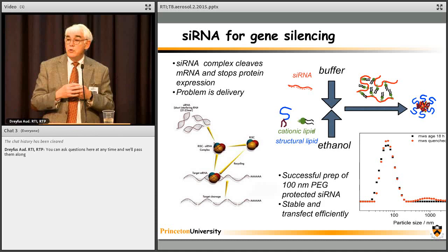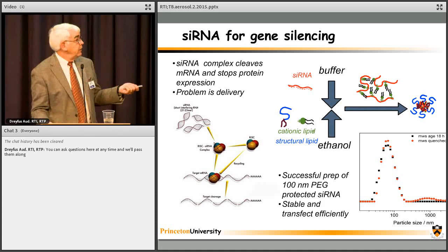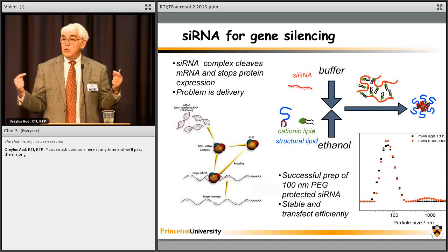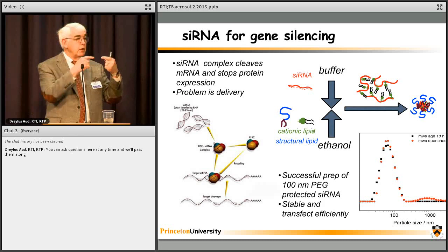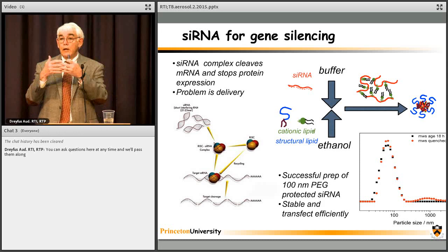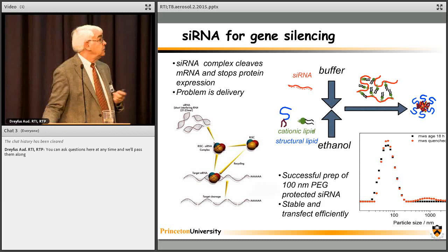And in fact, it works beautifully. Here are 100 nanometer particles or 80 nanometer particles we make by the rapid precipitation with the lipid coming in an organic stream and the siRNA coming in the aqueous stream. The electrostatics is fast enough to form this electrostatic complex, which is hydrophobic, to precipitate and to be protected by the PEG chains and to form these particles.